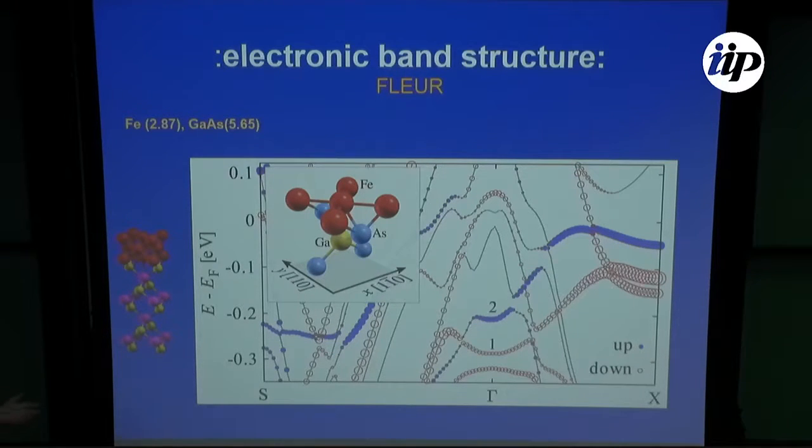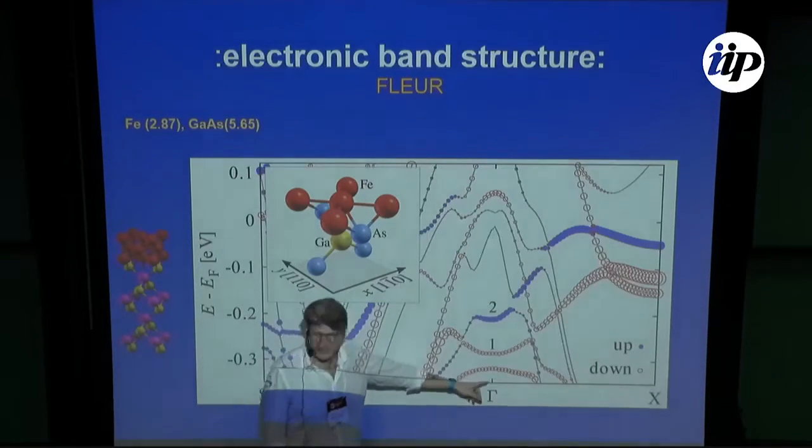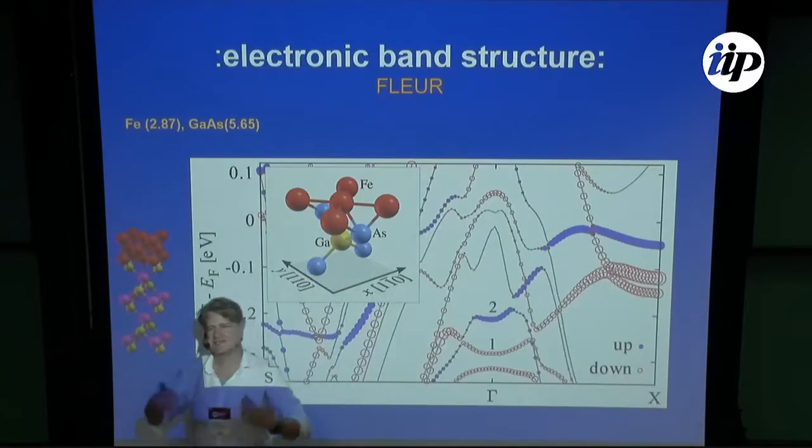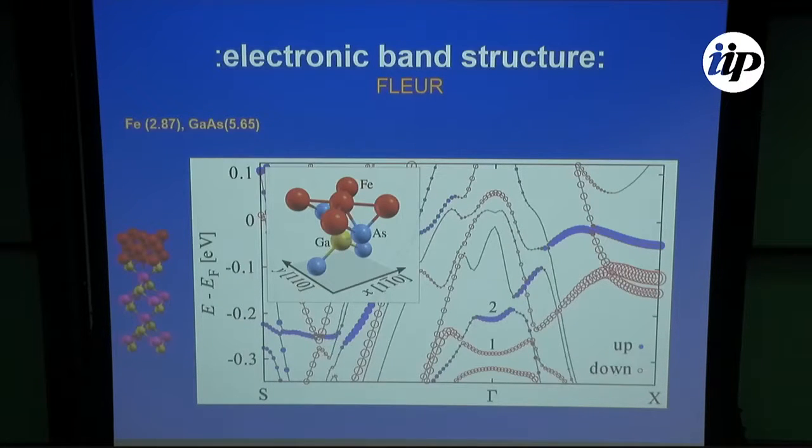So this is the electronic structure of a particular slab, 3 monolayers of iron on gallium arsenide, and you get some spaghetti. And then, where is your Rashba, where is your Dresselhaus, what is the spin orbit field? It's not so simple. To get the Rashba and Dresselhaus, linear or cubic, you look at the gamma point, because these are expansions around the gamma point, nothing more.